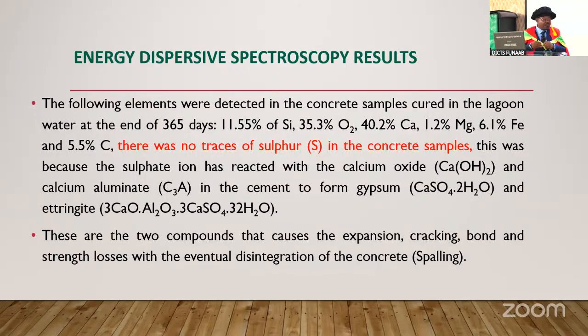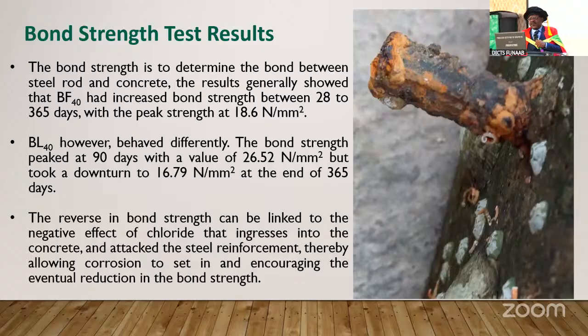That figure we saw the other time is as a result of ettringite and gypsum that were formed. Now, we look at the bond strength test. The bond strength test is to determine the bond between the steel rod and the concrete.